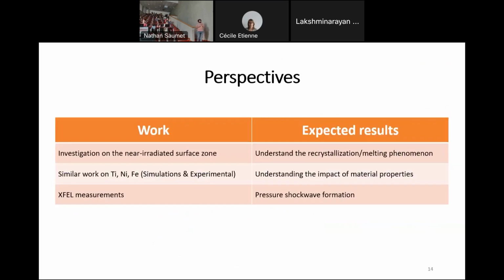So here are the perspectives for this work. As I just said, we'll investigate the near irradiated surface zone in order to understand how the melting and the recrystallization phenomenon impacts the laser peening. And we'll do similar work on titanium, nickel, and iron, both on simulations and experiments. And one of the next steps is also to do X-FEL measurements. So X-FEL is an X-ray free electron laser, in order to see the pressure shockwave formation and how it goes into the depth of the material in real time.